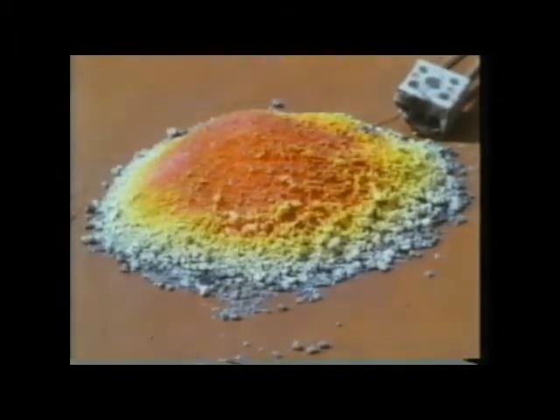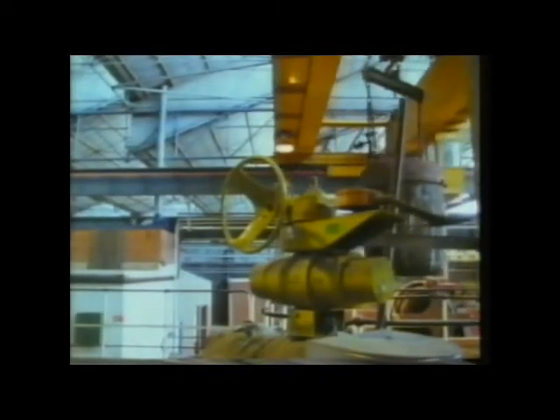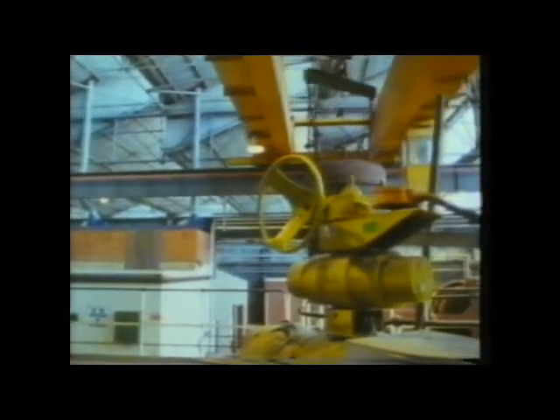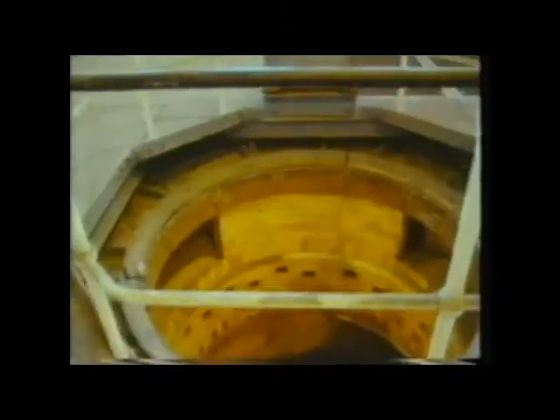Because titanium is very reactive, we must use an even more reactive element to win it from its compounds. This is where the sodium comes in. Because it's even more reactive than titanium, it'll remove the chlorine from titanium 4 chloride, leaving titanium metal and sodium chloride. The more reactive element replaces the other. Here's one of the steel vessels in which that reaction is carried out. It's lowered into a brick-lined oven, which can be heated up to a high temperature by gas burners.